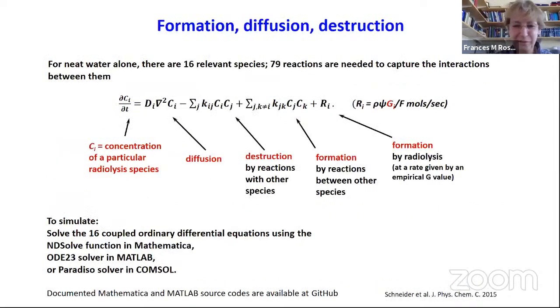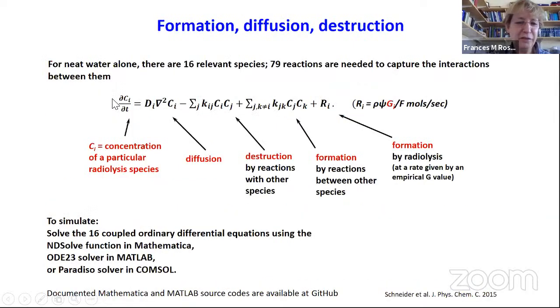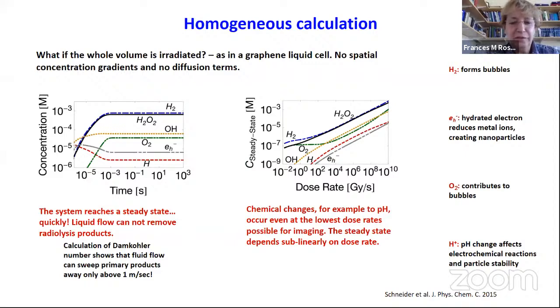How do we model this? Well, we have all of these species that I listed, plus a few others. They all react with each other. They can be destroyed by reacting with others. They can be formed through reactions of other species. And of course, they're being formed by the radiolysis reaction by the electrons, and they can diffuse away. And so this allows us to calculate the concentration of every radiolysis species using convenient tools out there. And so these calculations, which are based on empirical reaction rates and such like from the literature, tell us a lot about what's going on.